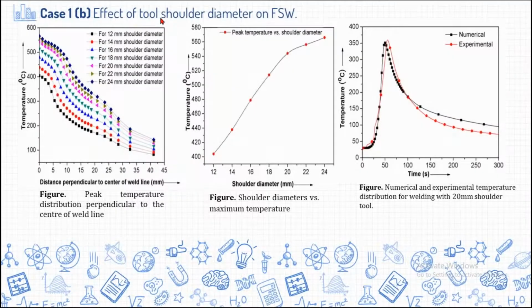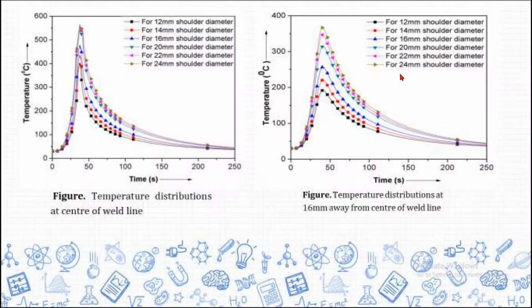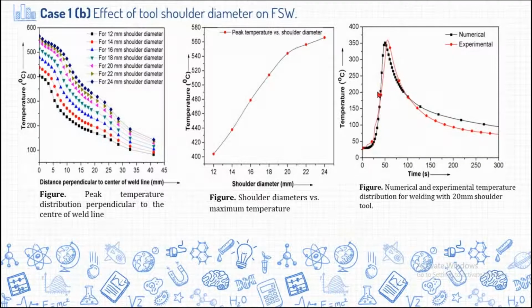After seeing this peak temperature, we did an experimental comparison with the numerical results. We observed less than 5% error between numerical and experimental, very close to the experimental result we observed over here.